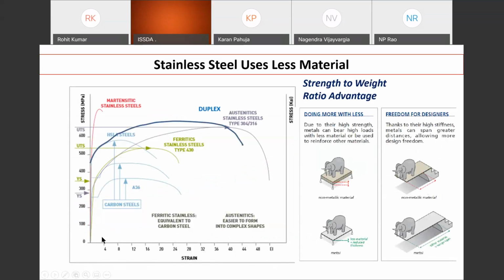Say for example, the strength, if we understand the strength to weight ratio. You all know that if you look at this graph, this is the stress versus strain curve for carbon steel, compared to some of the stainless steels like austenitic, duplex, ferritic, and other grades. Some of the stainless steels, like austenitic stainless steel, have this property of strain hardening. By strain hardening, I mean if you bend it, you do some kind of reduction on it, then its strength starts increasing because of the strain hardening effect, with only a little loss in ductility.